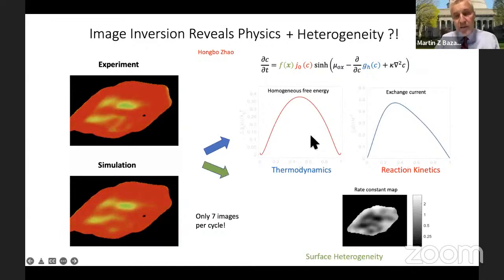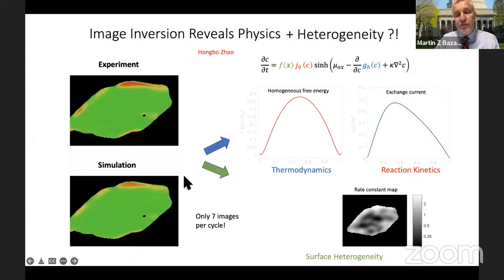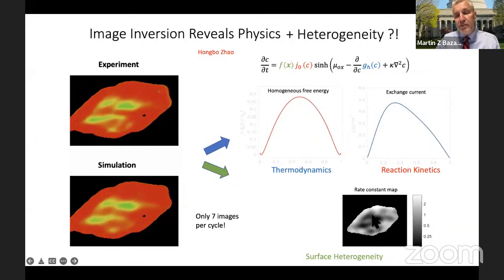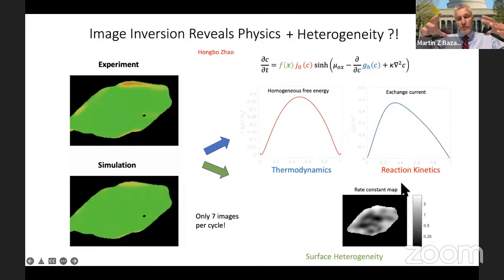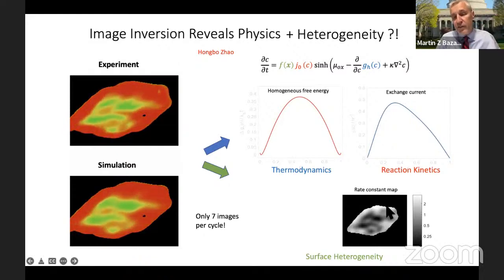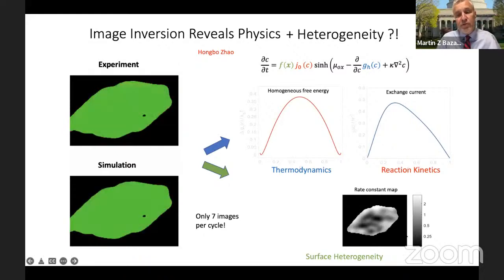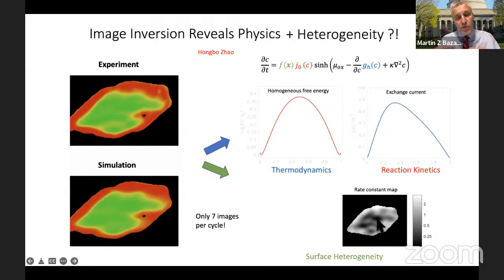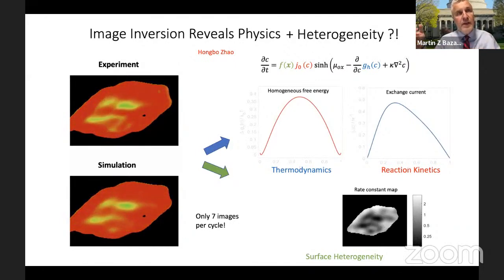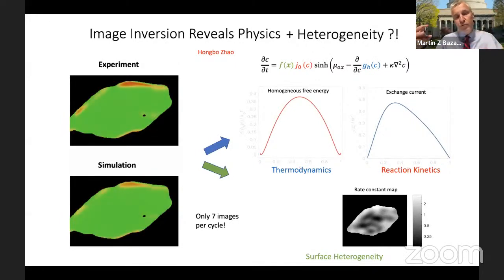In addition to that, we can do pretty well with just those 2 functions, but to get the really good match you see here, we also infer a spatial dependence f(x) here for the rate constant. So basically using some eigenfunctions that represent that shape, we sort of assume, or we learn actually, this distribution of rate constant over the surface. And the variation here in the shading is by about a factor of 3. So basically, as we had already guessed in the original experimental work, there are fast and slow regions on this